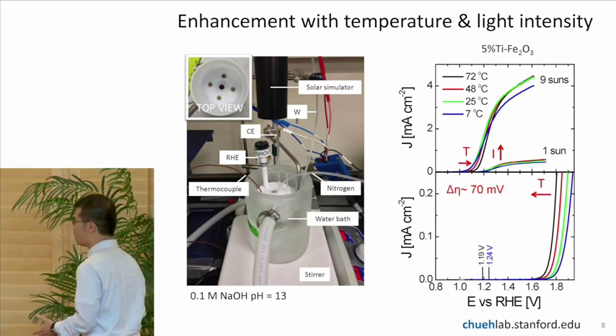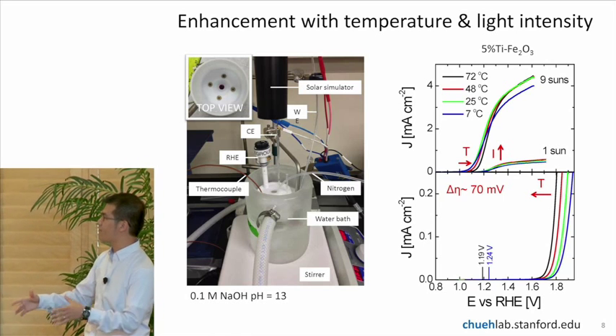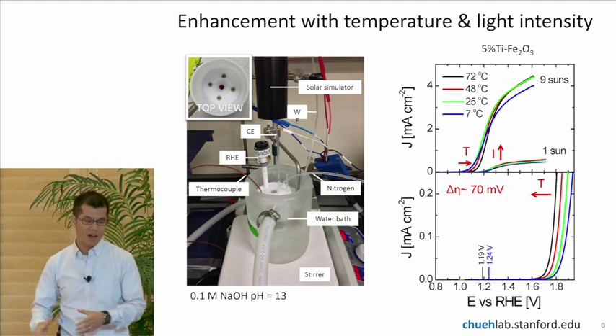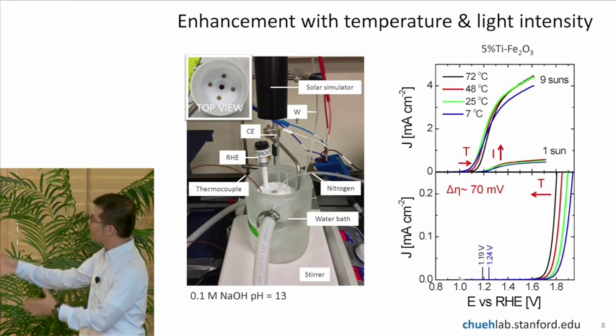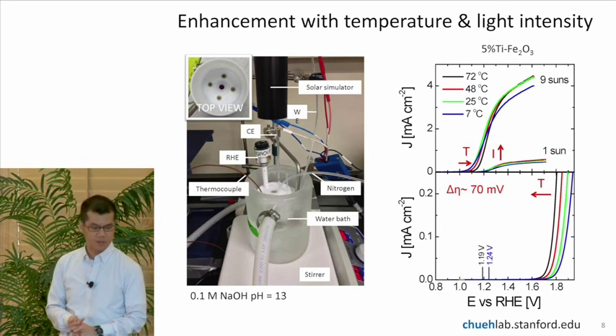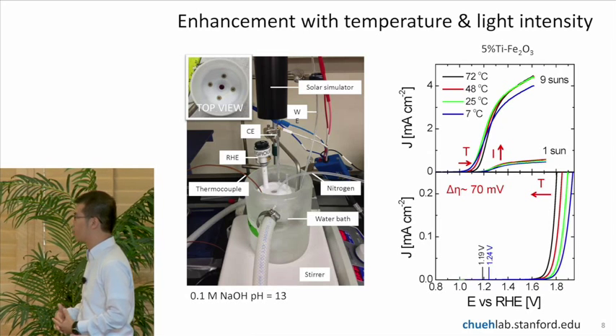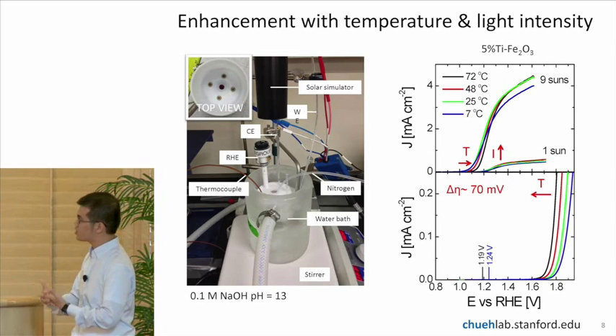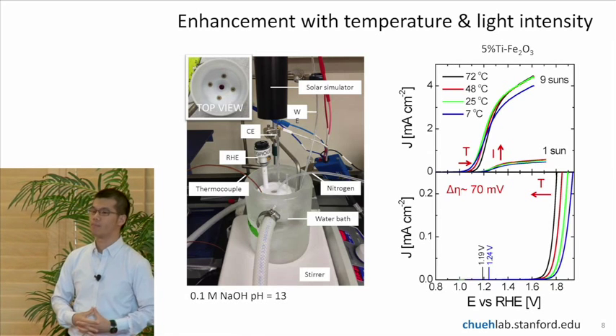And what we did next is we designed an apparatus not only to control the light incident on the cell, but also to control the temperature among various other things. So the setup on the left shows that we have a thermostatic controller, a water bath basically, to set the temperature of the cell. And we have a liquid electrolyte system that allows us to go close to 100 degrees Celsius. So this is a liquid-based system, so we're capped basically by the boiling point of water. So this is a standard electrochemical experiment,